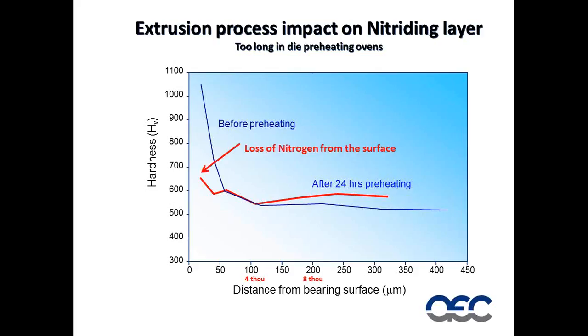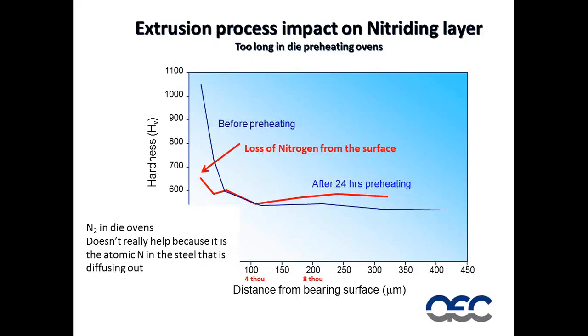Now, some people say putting nitrogen, which is N2 gas, into the die oven makes all this problem go away. I wish it was that simple. The problem we have is that what is diffusing out of the steel is atomic nitrogen. The second that atomic nitrogen is free of the steel surface, it reacts to make molecular nitrogen, and it's gone. Molecular nitrogen does not diffuse into steel.